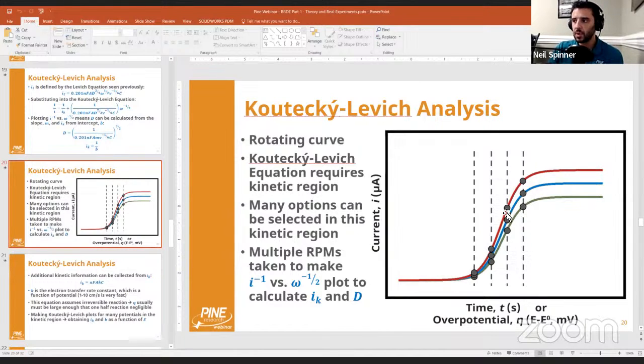But it might just require trial and error, in particular, as I said, where you're taking your Tafel slope, and then backing up and making sure all the other parts of your experiment are operating properly, that your curves actually are good, your limits, your sweep rates. You could try slowing down your sweep rate. If you're sweeping too fast, maybe that's contributing. There's some of these trial and error of your experimental parameters that might help clarify the data too.